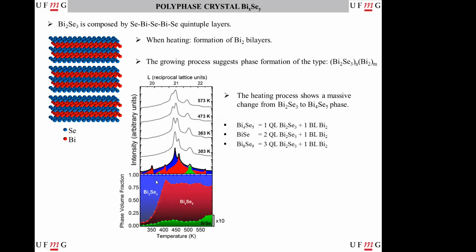Here we have an example, an image using X-ray diffraction. Here we try to estimate, over the temperature, the formation of the new phases of bismuth selenide. Here we can see that there is a great change from Bi2Se3 to Bi4Se5, whose unit cell is the combination of one quintuple layer and one bilayer. If we continue heating the material, it will start to form other kinds of structures that we can see here.